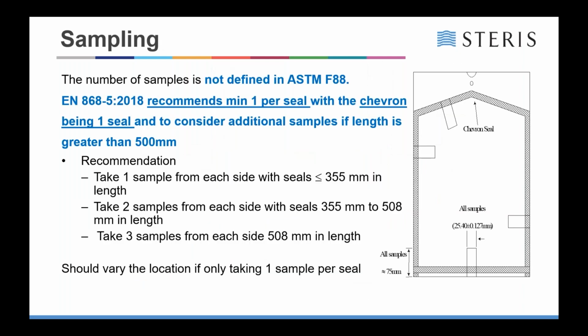In relation to sampling, none of the standards will really tell you that you should take samples from this side or that side or where you should take them. The only one that does is EN 868, which recommends that you take a minimum of 1 per seal and that you treat the chevron as a single seal. So you're not taking 2 samples for that. And anything that's over 500 millimeters, you should look at taking extra samples.